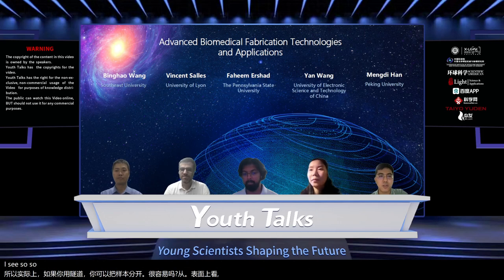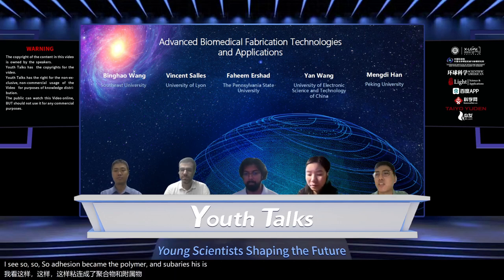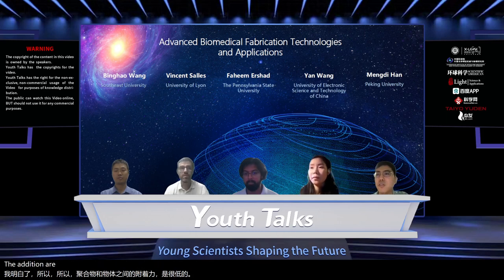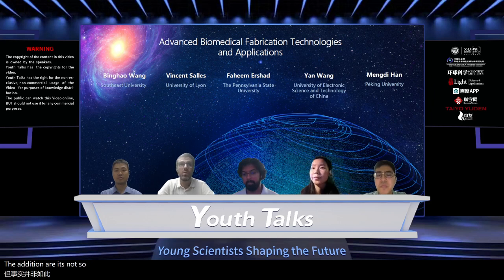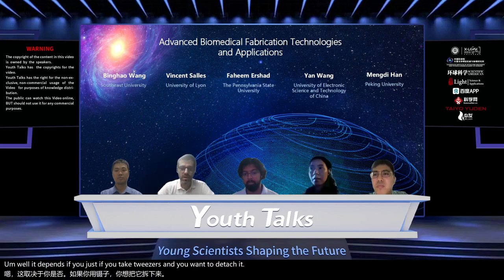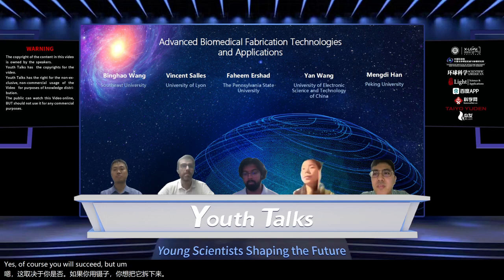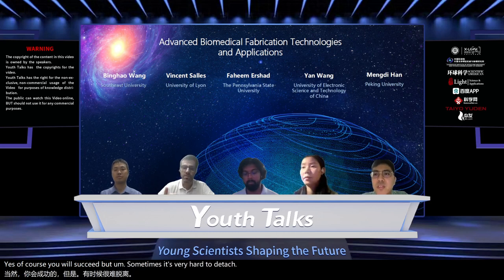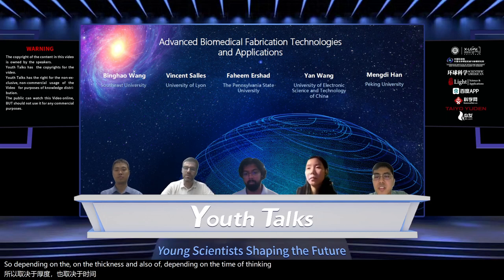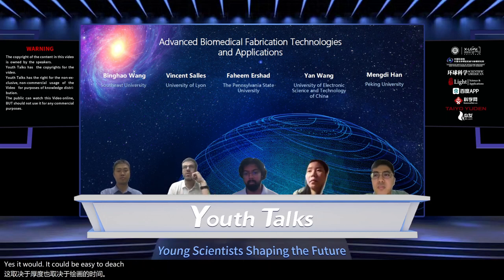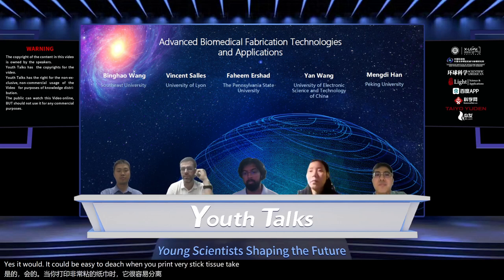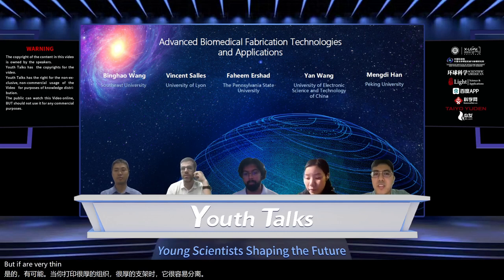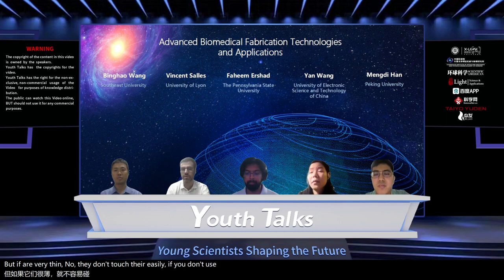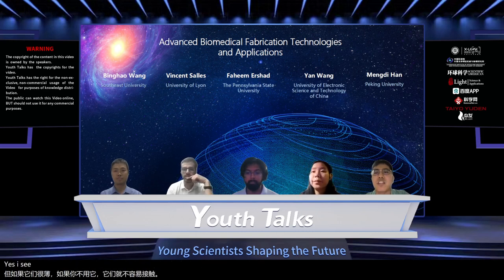I see. So the adhesion between the polymer and the substrate is quite low, right? The adhesion, it's not so low. Well, it depends. If you take tweezers and you want to detach it, yes, of course you will succeed. But sometimes it's very hard to detach, depending on the thickness and also depending on the time of printing. So yes, it could be easy to detach when you print very thick scaffolds. But if they are very thin, they don't detach very easily if you don't use ethanol, for instance. Yes. I see. Okay, thank you. You're welcome.